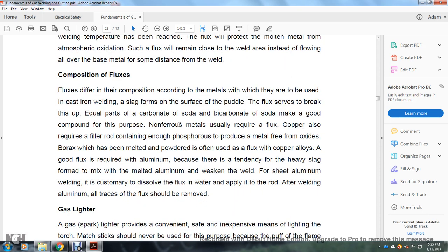Composition of flux. Fluxes have different compositions according to the metals to be used. In cast iron welding, slag forms on the surface of the puddle, and the flux serves to break this up. Equal parts of carbonate of soda and bicarbonate of soda make a good compound for this purpose. Non-ferrous metals requiring flux: copper requires filler rods containing enough phosphorus to produce metal free from oxides. Borax, which has been melted and powdered, is often used as a flux with copper alloys.